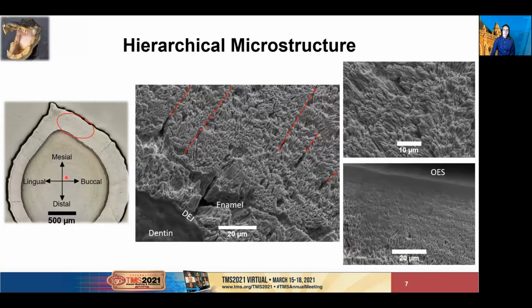Now we are looking from the cusp down towards the root on a transverse cross-section of an alligator tooth, again polished and etched. Close to the dentin enamel junction, you can see some relatively large gaps separating repeating columns of diverging hydroxyapatite crystals. The boundaries between adjacent columns are then delineated by convergent crystals. I've pointed out some of them in red here for you. The overlap of one sheaf of nanocrystals onto the next causes a slight serration, which is responsible for the so-called growth lines we saw before.